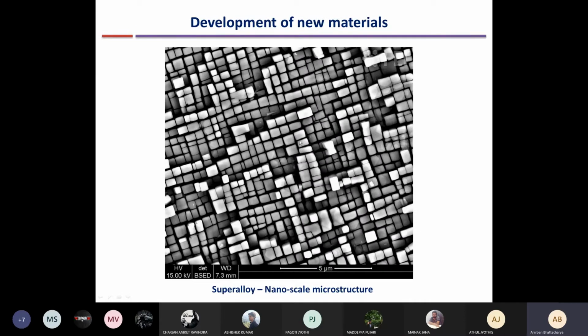Dislocations are defects present at the atomic level, and any deformation, like elongation in a tensile test, occurs by movement of dislocations. This gamma gamma prime microstructure hinders that movement. A dislocation cannot move through the square blocks. It has to move through the channels, which provides much more resistance. So just by modifying the alloy, the strength or creep resistance could be significantly improved.